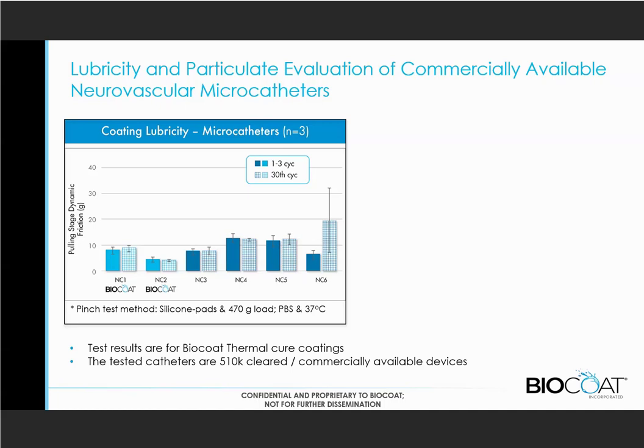So what you're looking for is low numbers and then not changing much over those 30 cycles. And you can see that actually 5 of the catheters have low friction and also good durability. There was a 6th one that started with an initial good friction, but you can see that it started wearing off over time. And not only that, there was variability in that catheter, indicated by the higher error bars there. So this shows one where maybe the durability is not quite as good. The other ones, though, are around 10 grams of force when we're applying 470, that's a really good coefficient of friction. And so these were, as I mentioned, all 510(k) cleared commercially available devices.